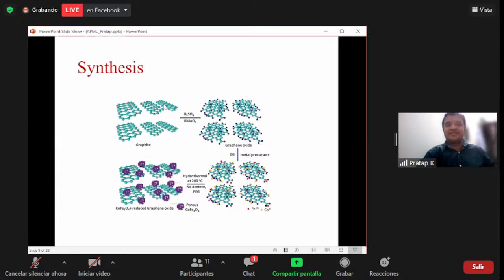This is the graphite, and we are preparing graphene oxide by the modified Hummers method. Using the solvothermal procedure, we add the metal precursors, ethylene glycol and so on, and we are preparing cobalt ferrite anchored on the graphene sheet. So this is the reduced graphene sheet with cobalt ferrite on it. This is the schematic of the synthesis. Graphite to reduced graphene oxide is obtained by the modified Hummers method, and from there the composite of reduced graphene oxide and cobalt ferrite is obtained by the solvothermal method.